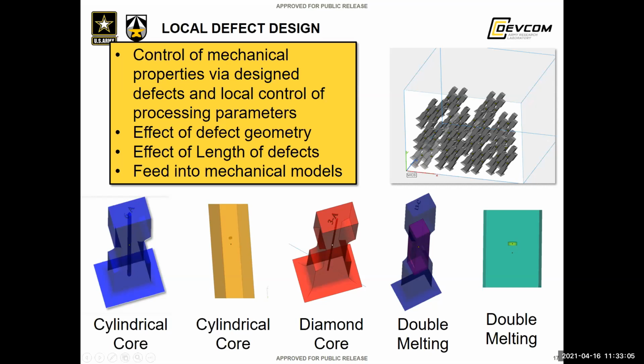This is an ongoing study, so I don't have the results yet, but we're looking at the effect of having a round defect core, say double melting in the middle, versus a diamond shape, something with a lot of corners that could be potential crack initiation sites, as well as the length of the defect, whether it be a couple layers, 1 layer, 3 layers, 20 layers, versus it going through the whole entire gauge section.